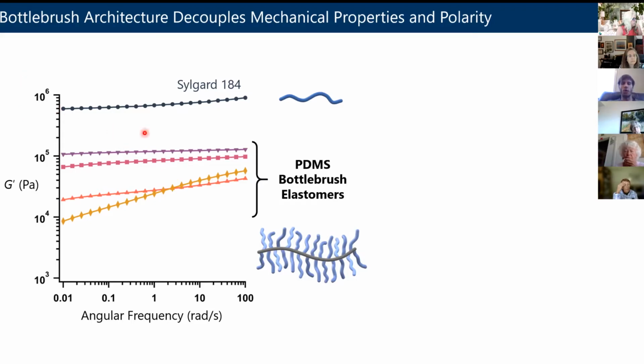And you can see now, we've made some bottlebrush polymers. The blue chemistry for the side chains is identical to the blue chemistry of Sylgard 184. All we've done is changed how they're linked up together. We've gone to this more complex branched architecture. You can see when you do that, you drop the stiffness down, well, to 10 to the 5 or even 10 to the 4. These are 4 different formulations that we've synthesized.